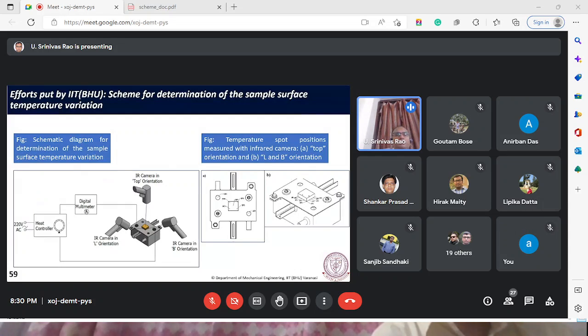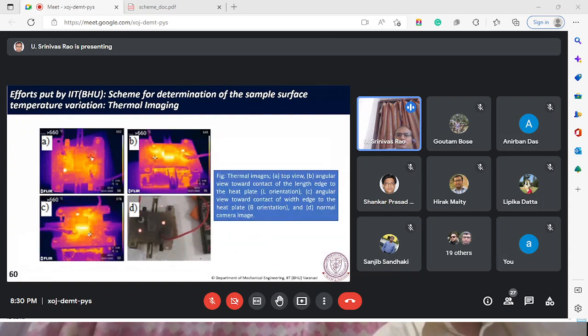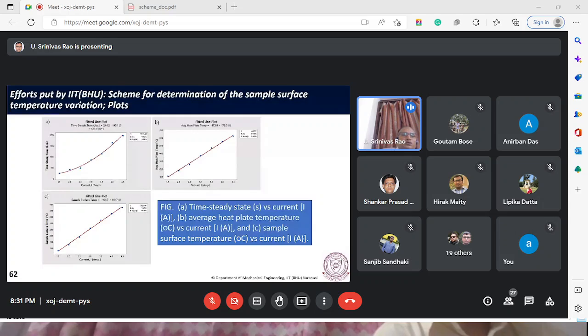And then this is characterized through some heating tests. So at different voltages, what are the temperatures obtained? Those things are characterized, and through that we got these characteristics at different currents. So with time, how it is varying, and then current versus temperature obtained. So here the maximum obtained is somewhere here, that is 426 degrees. And it is giving a mostly linear curve. The average heat plate temperature is a little more than this, which is the specimen sample temperature. This is the heat plate temperature.